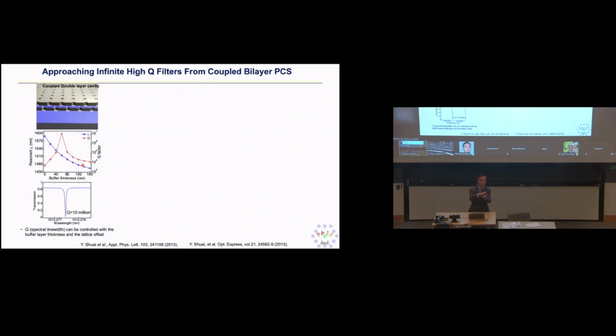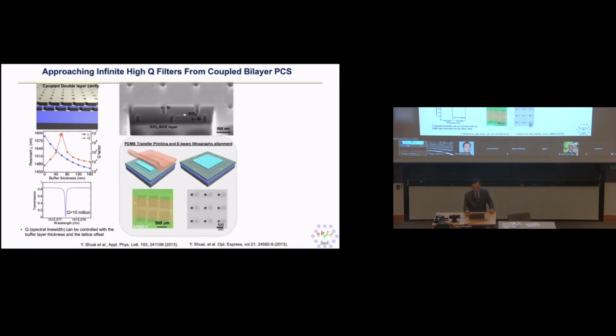The second one is high Q cavity. I mentioned you can do that kind of offset lattice. And potentially you can get 10 million, whatever theory, infinite Q structures by controlling the separation of two photonic lattices, also the lattice offset of the two layers here. So here's just an example of how we did it by the transfer printing process. We make a first layer here, and we do a thermal oxidation to form a thin oxide, and then we transfer an unpatterned membrane on top, and then we do another e-beam process on top by an aligned e-beam process. So then you can control the offset of the two layers here. And the separation can be controlled by this thermal oxide in between.